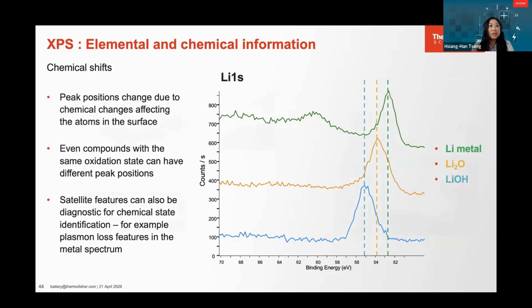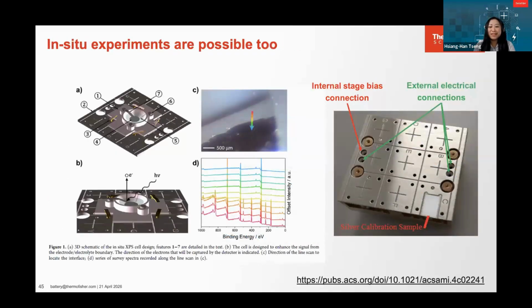Next slide, please. That's very typical with XPS, but I would like to add an example showing that we can actually do in situ experiments as well. That's very exciting if you think about it. You don't just look at your battery materials, you can also apply bias in situ. So here is a case where we perform in situ electrochemistry experiments, but do remember that the electrolyte will have to be UHV compatible, such as the kind of ionic liquids used in this study, and you can find the actual reference. On the left-hand side are the schematics that show the kind of setup you need.